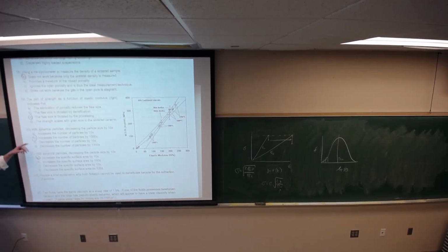For spherical particles, decreasing particle size by a factor of 10 increases the number of particles by a factor of 10 to the third, because volume scales with the cube of the radius, so when the size gets smaller, the number of particles goes up. Surface area is linear with size, so decreasing particle size by 10x increases the surface area by a factor of 10.